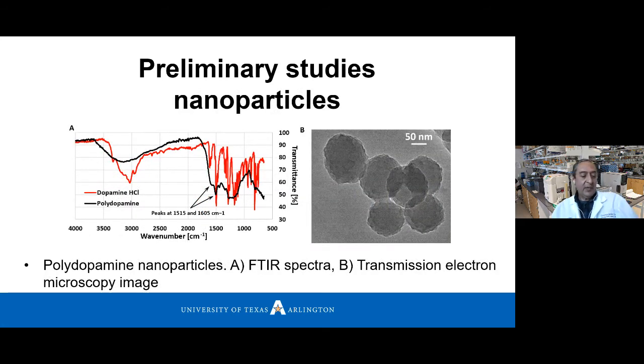Also, we have been working on the development of nanoparticles. In this particular case, we prepared nanoparticles of polydopamine. Just remember that in our design, we're going to be using polydopamine. These polydopamine nanoparticles, we confirmed that they are polymerized according to this spectra. And in the image to your right, you can see a transmission electron microscopy image showing these polydopamine nanoparticles.